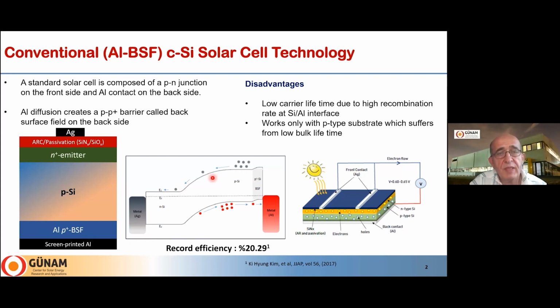And here you see the band structure of this cell: conduction band, valence band, and metals on both sides. We have a P+ layer here, which is the backside of silicon. And when the incoming photons are absorbed by electrons, they are excited to the conduction band, and they move towards the N region, and holes move towards the P region, to the other side, to the back side of the cell. And then you collect them and you form the current. So here you see the schematics of the solar cell, and you have two terminals, and electron flow takes place from the front side and then goes through the external load. So you generate current and power in this way.